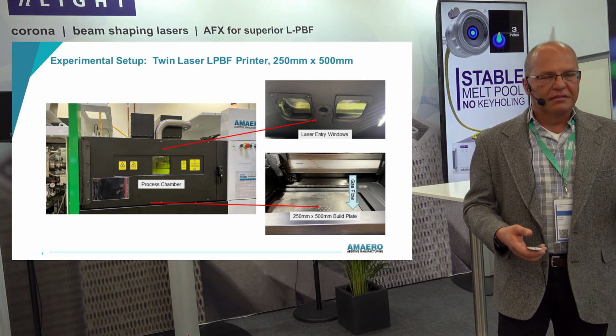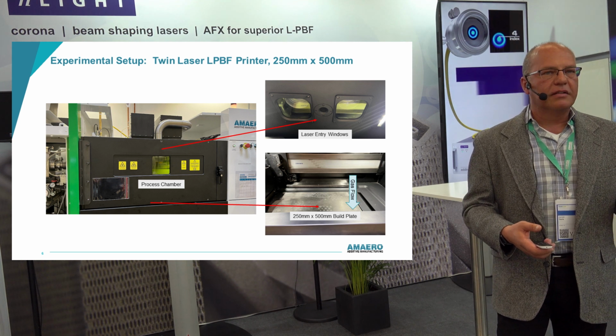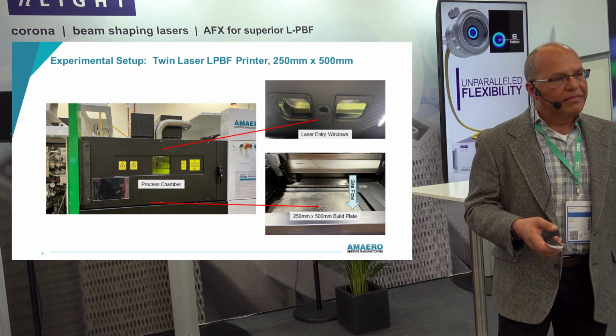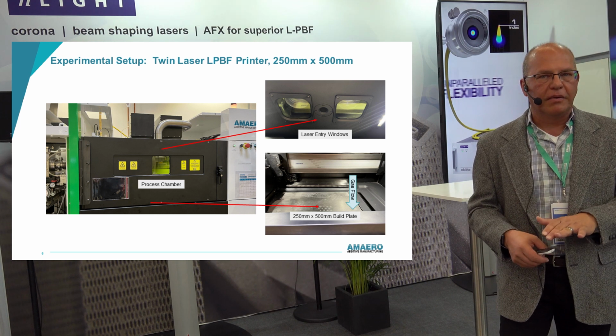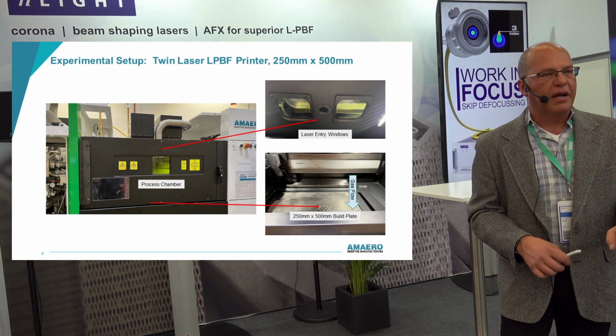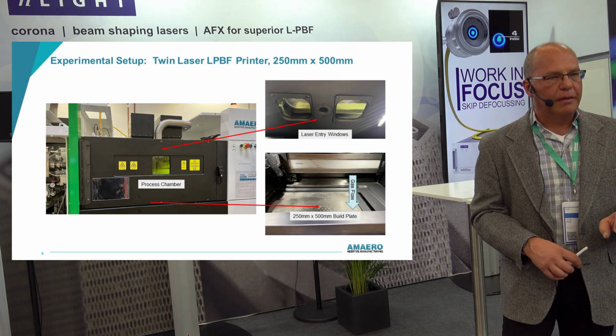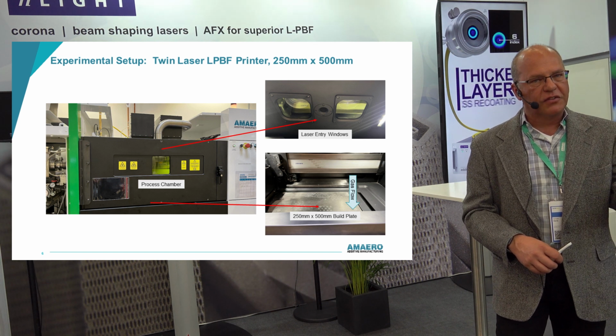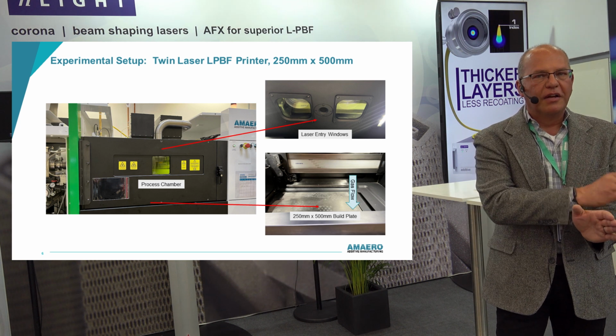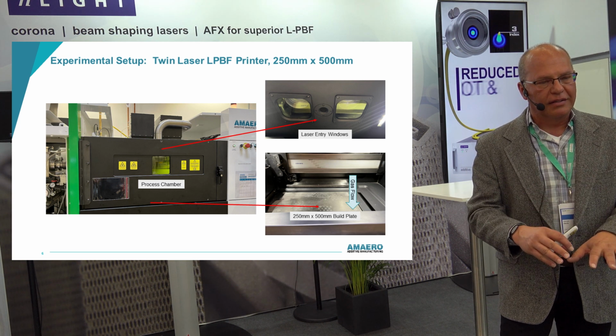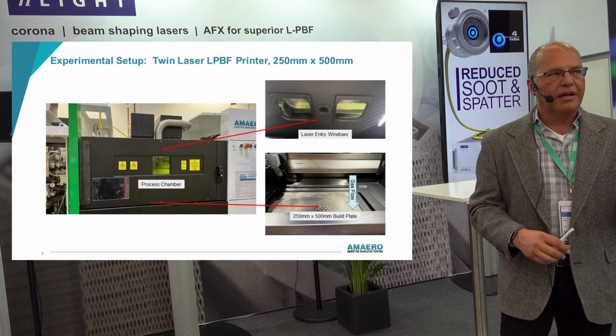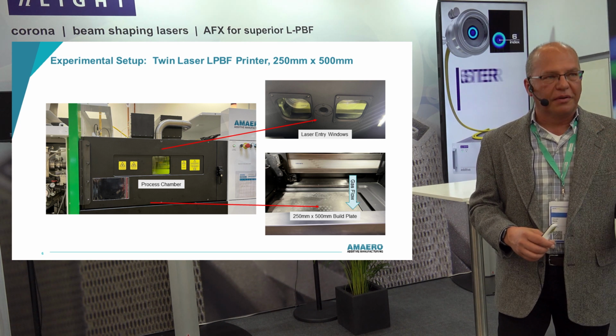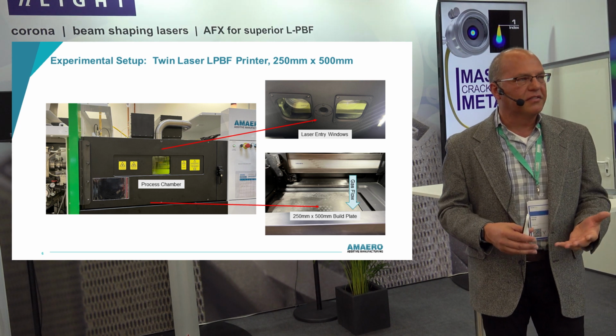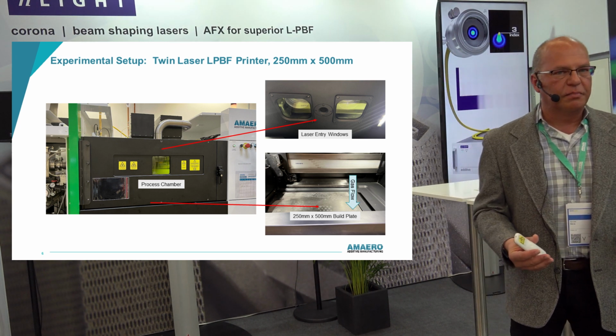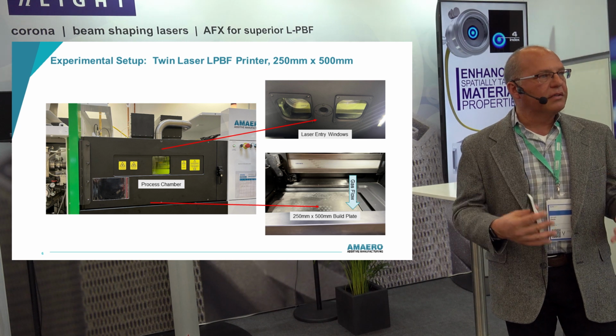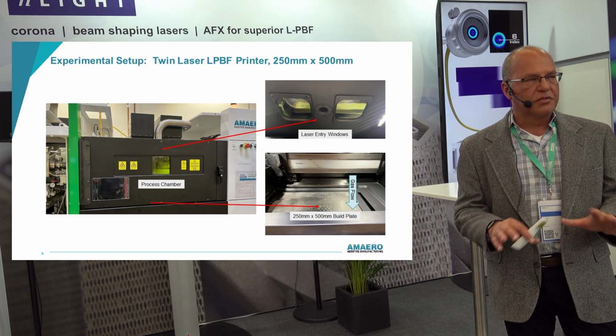Well, you increase your plate heating to its maximum potential, about 200 C, spread very thin layers of powder, 30 micron, pour in a lot of laser power, which means we're generating a lot of vapor, and then you scan very slowly so that it doesn't cool off quickly, and that's how we reduce the thermal gradient. So we generated a lot of condensates, and we created horrible productivity. We're scanning at like 600 millimeters a second, which is half of a normal scan speed. You do that, and you can create really nice-looking H-13 microstructure.